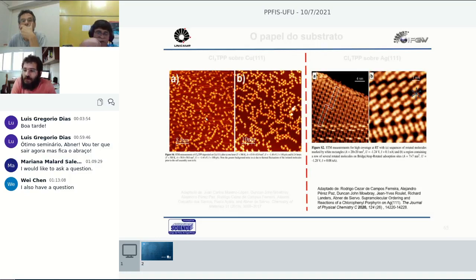Yeah. And with that, in this particular work, we could measure the position of the molecules like Brownian movement. We could measure the position of the molecules, do statistics, plot an Arrhenius plot, and extract the energy barrier for translation, which was around 1 eV. That means with a 1 eV barrier, the molecule cannot really travel freely on the surface because you have this interaction of the nitrogen to the surface. This is the reason why the molecule is not like a free gas on the surface.